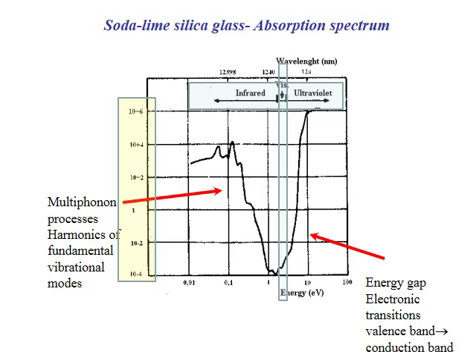Silica is transparent in the visible, as everybody knows. However, the minimum in absorption is not in the visible range. The minimum in absorption for silica glass occurs around 1.5 micron. That is therefore the wavelength of choice for telecom signals.